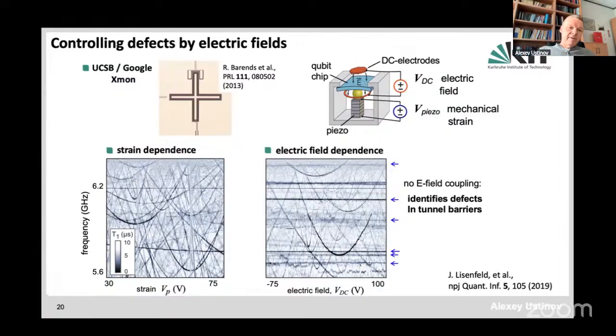And remarkably, the difference between the strain dependence on the left and the electric field dependence on the right is that some of the defects stop changing their frequency. So you see that some defects are not reacting to the electric field. Some do, but some not. And actually, those defects, we believe, are defects in the tunnel barriers. So they're inside the superconductor, covered by superconductor, and therefore they don't really see stationary electric fields applied from outside. This procedure, applying electric field and strain control, allows us to distinguish between defects on the surface and defects inside the tunnel junction.